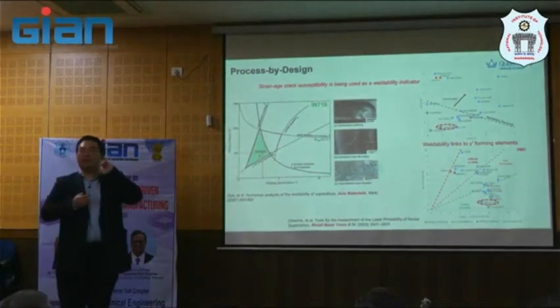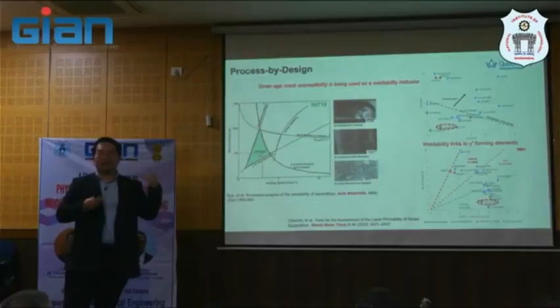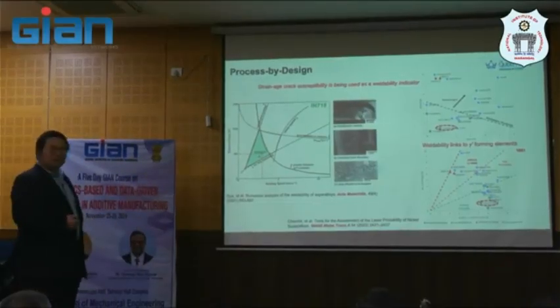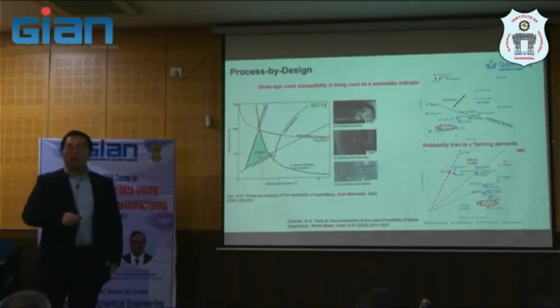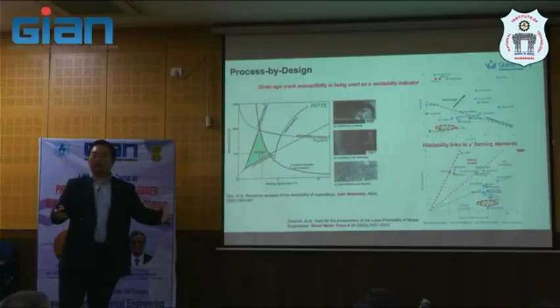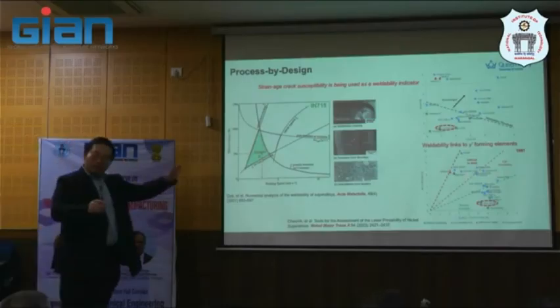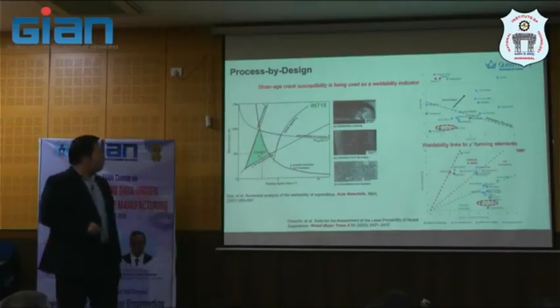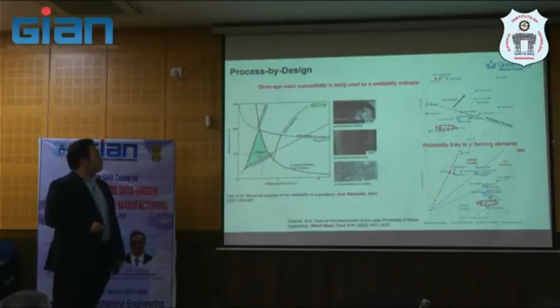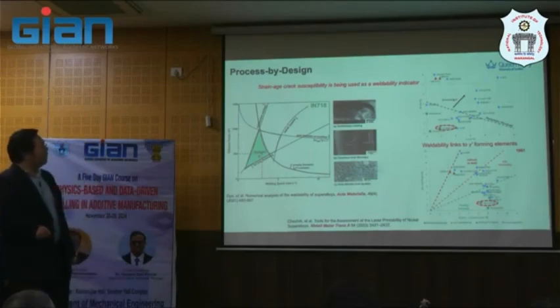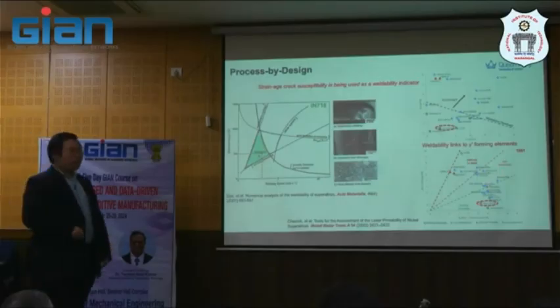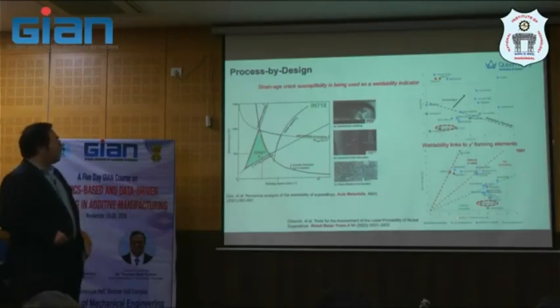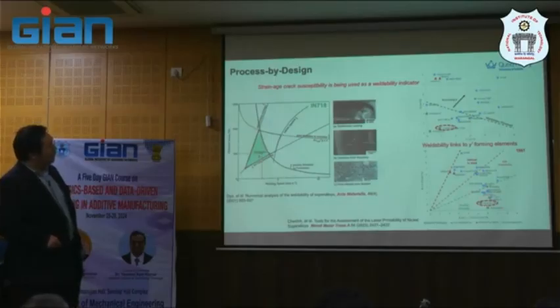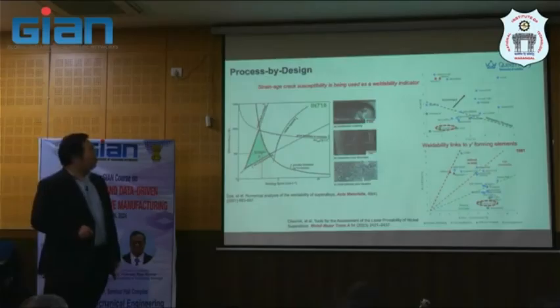This is my first question, actually, when I was a lot younger, and it inspired me to dig out more. Why? There's no gamma prime. Why do you link this? This is purely based on empirical study on a particular set of material at that time. Again, some other people proposed this diagram again, but they later looked at more combinations of gamma prime plus other phases, and again said this is based on experience and observation from experiment, and tried to link that there is some readily weldable material in this zone, but again not completely, because some zones are mixed up with the red and the blue dots here. So that's very weldable, I don't know what it means as well, and then difficult to weld, or very difficult to print.